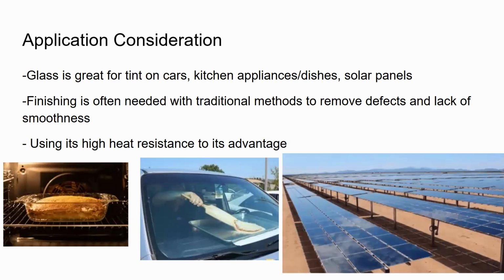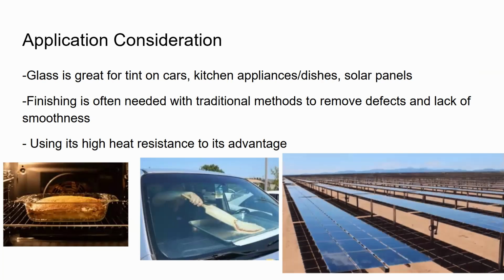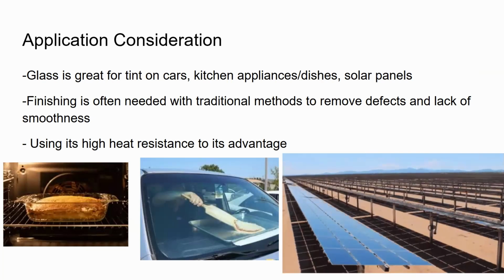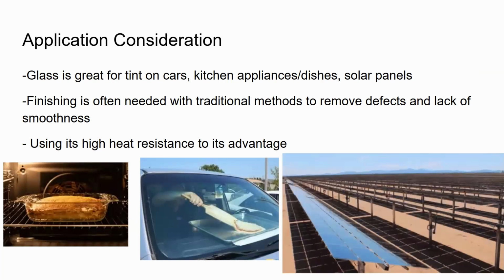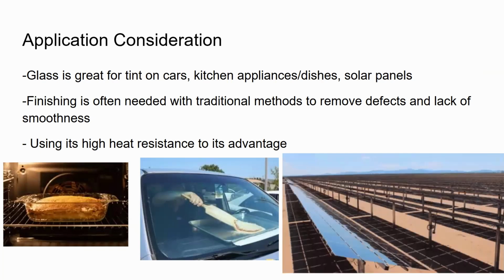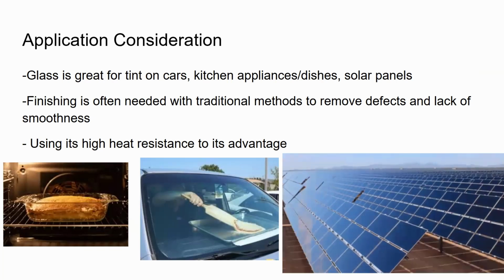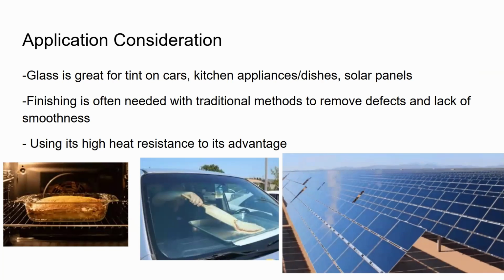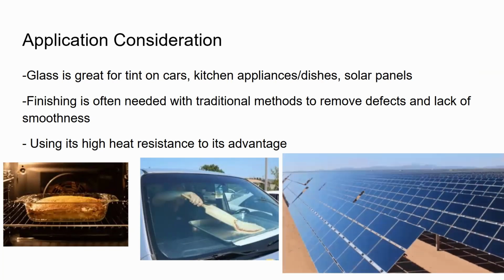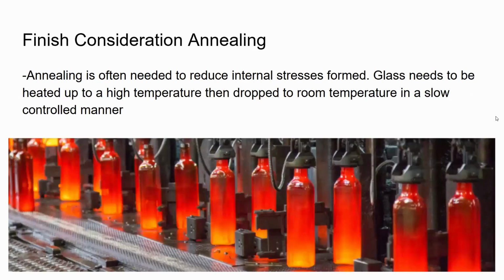So with all those things in mind, you want to use the benefits of glass to strengthen it even further. Glass, when it's typically made, will have a little bit of defects. It'll have a little bit of roughness on the surface or corners that aren't perfectly straight, or it could be brittle. So we use its highest advantage to benefit it more. Because it's so good at resisting heat, you go through a process called annealing. Annealing is when you heat up a glass to a very specific point, similar to metals, and then you drop it to room temperature in a slow, controlled manner. What that does is strengthen the material while removing the finishes that are rough or uneven on the surface. So it has two benefits at the same time.